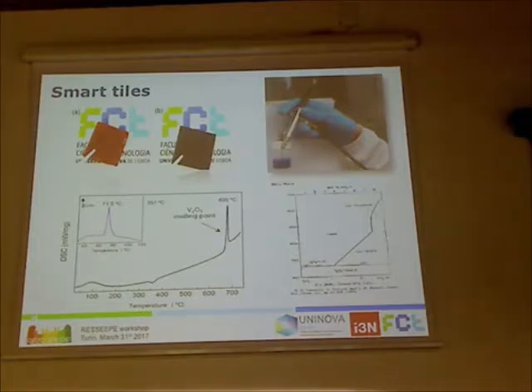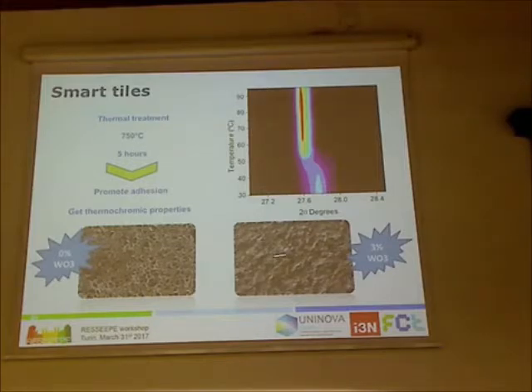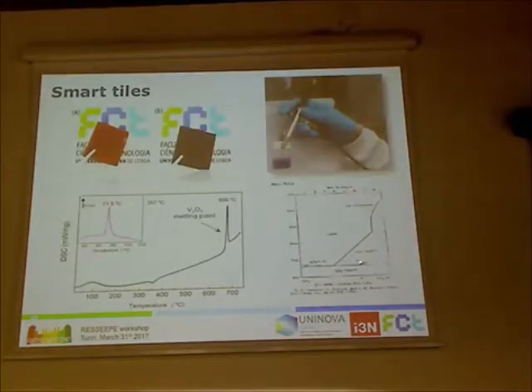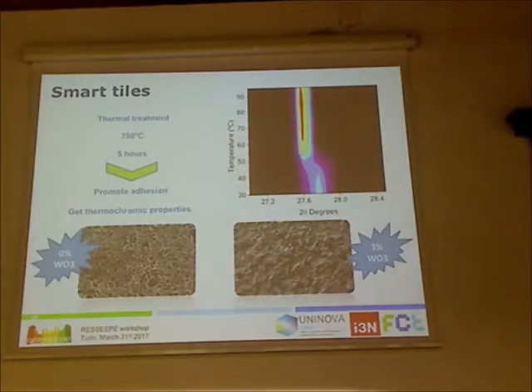For VO2, you have something very similar, and you can take advantage of it. If you heat during that treatment I mentioned, applied over the tile, and do the heat treatment in a reducing atmosphere, the particles partially mix, creating a kind of liquid phase between the vanadium oxide and the quartz that's there - the SiO2 on the glass layer of the tile. They partially melt and mix with the tile's glassy cover, so they get attached to the tile during this heat treatment. This treatment promotes adhesion and also allows stabilization of the monoclinic phase of VO2.